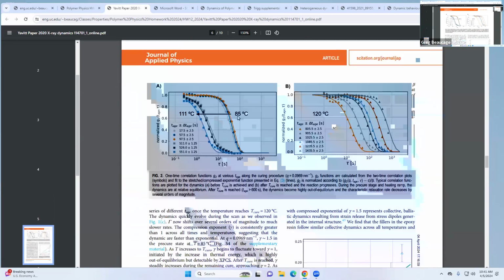So those are some of the figures we put in, showing that kind of drop in the dynamics from the one-time correlation functions as we started going through that ramp. So things speed up. And then once you hit the cure state, they cure out. That same plot there.